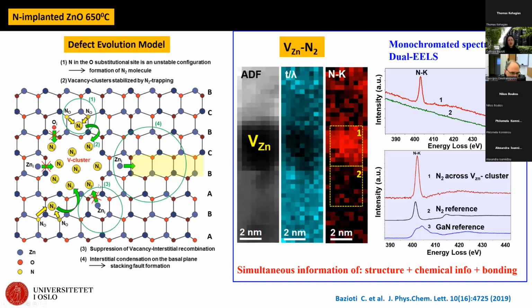Then this phenomenon suppresses the recombination of zinc and oxygen interstitials that all condense on the basal planes and create all these stacking faults that I showed before. And this also explains the reverse annealing phenomenon and the dramatic increase in the defect concentration even after annealing in this system.